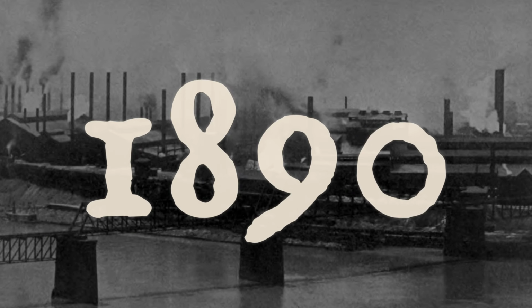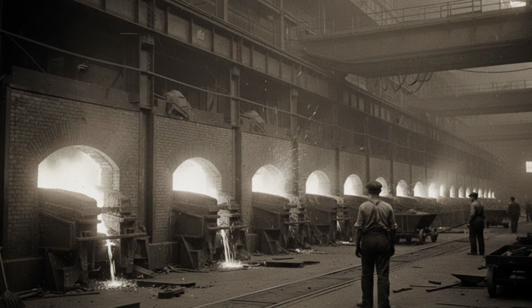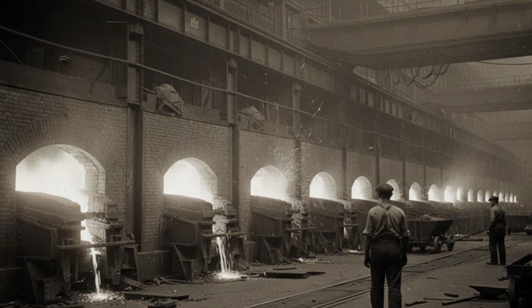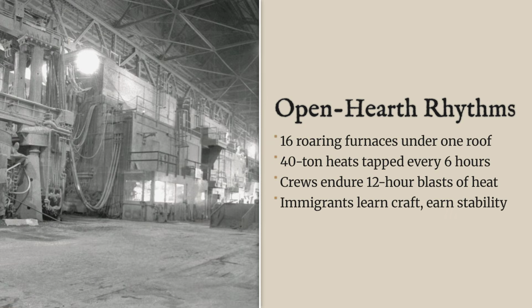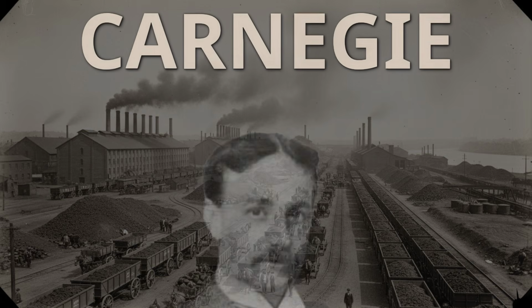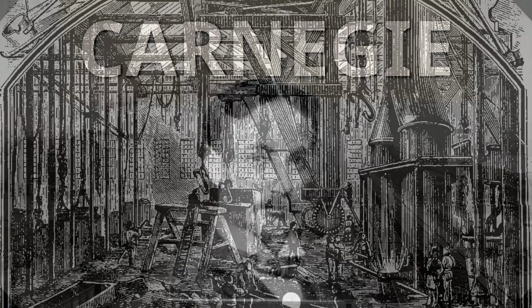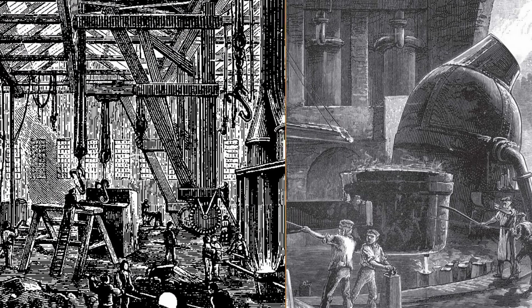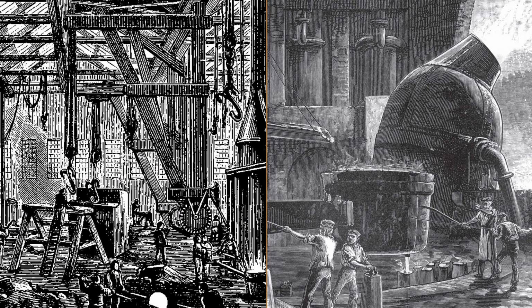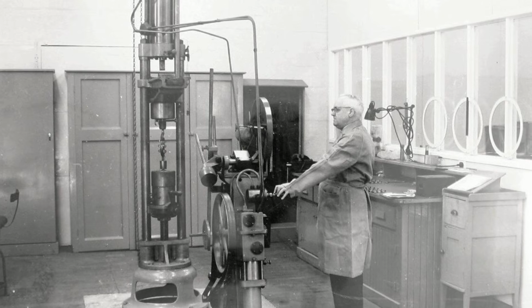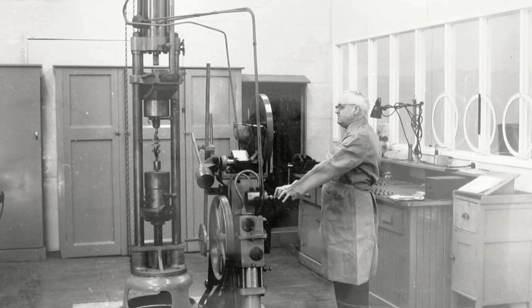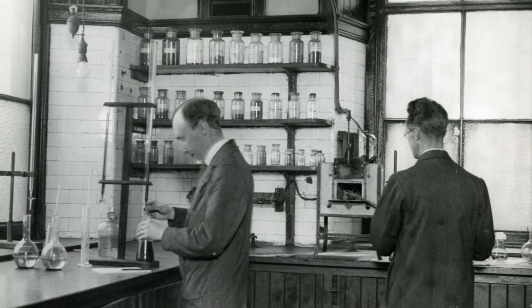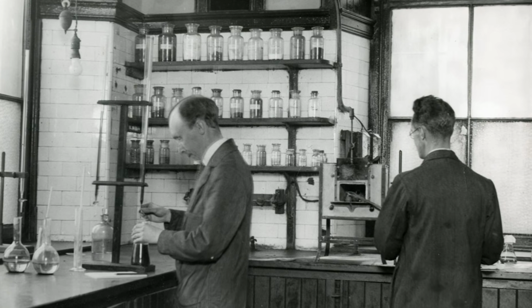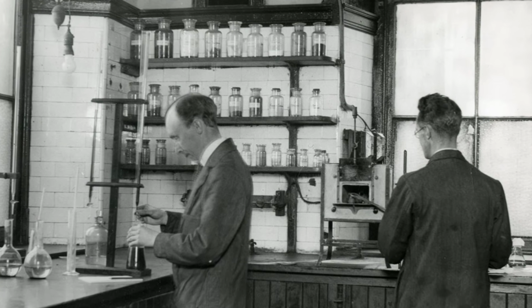By 1890, the Open-Hearth shop at Homestead was already one of the largest in the world. 16 furnaces in one building, each producing 40 tons of steel every 6 hours. Carnegie had invested heavily in the Open-Hearth process, specifically because it produced a higher grade of steel than the Bessemer converter, steel with lower nitrogen content and better consistency, suitable for structural applications that demanded reliable material properties.